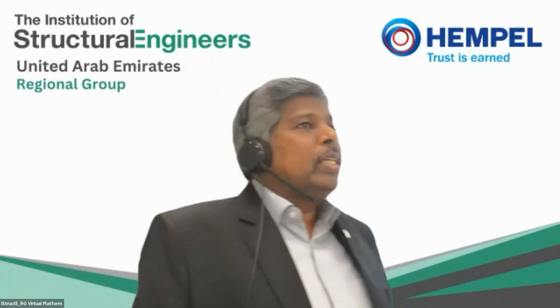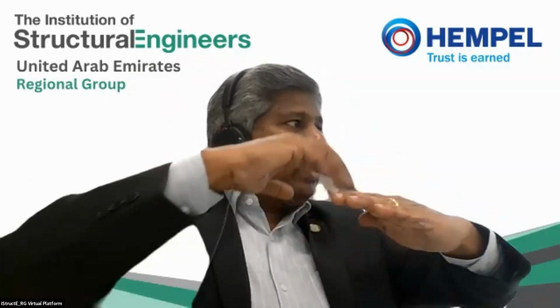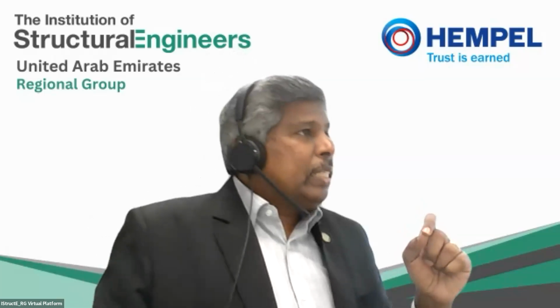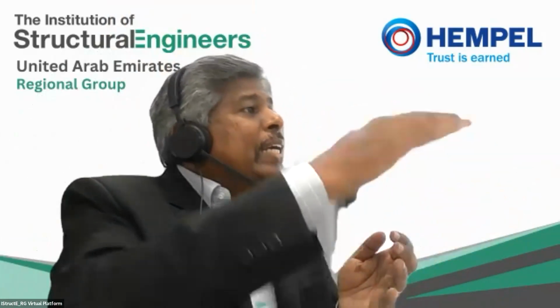Yeah, I think that's an important question, because what you're doing is you have steel, then the zinc rich primer intimate with the steel, and then a barrier mid coat and a polyurethane top coat. Generally, over a period of time, if it is in a very humid environment, the moisture can slowly penetrate, even if there is no pinhole. But worse than that is during maintenance, if somebody goes in and damages the coating, there is a holiday.